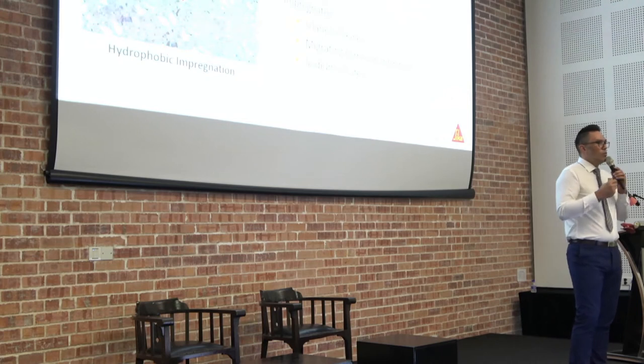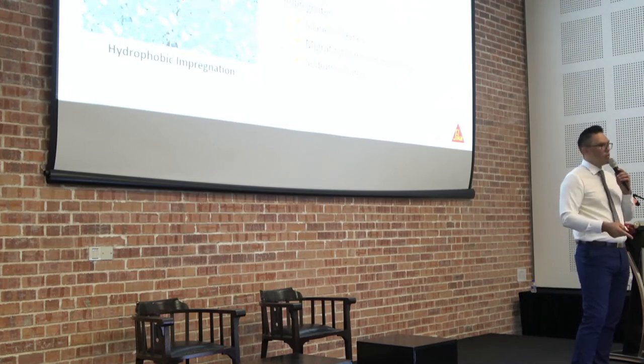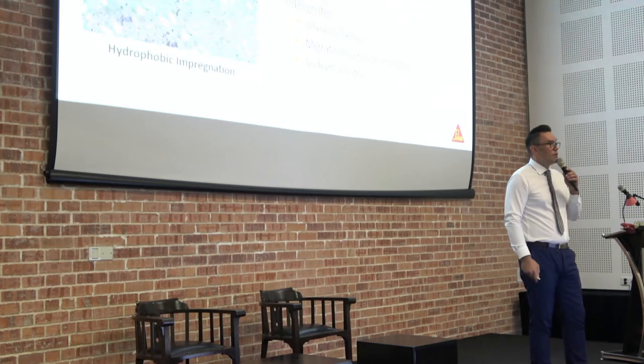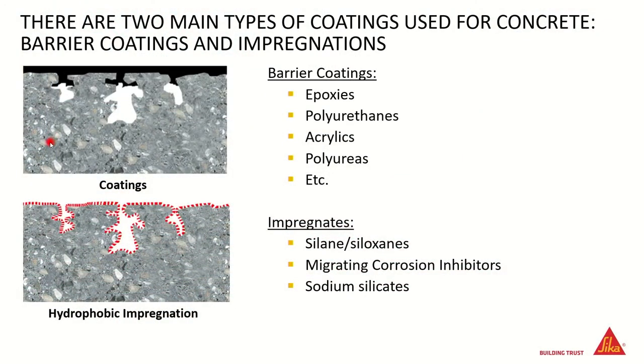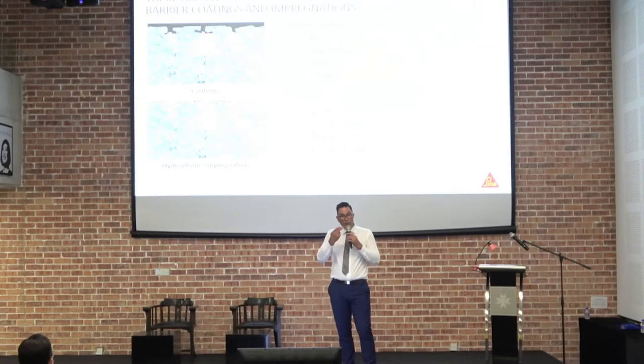For reinforcement to start degrading or corroding, you need basically three things. You need oxygen, which you'll get in concrete anyway. You need moisture, and then you need something else that's making it corrode. If you put a barrier coating on, then you exclude the moisture, and in certain circumstances you can also exclude the oxygen, so you won't get corrosion on the steel. It is a good option for protecting the reinforcement.